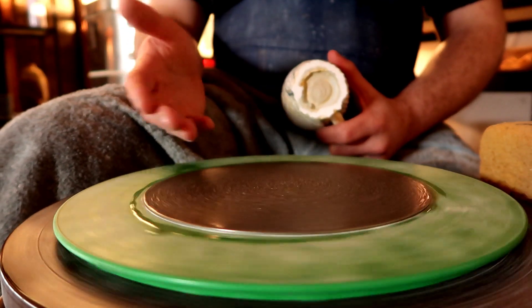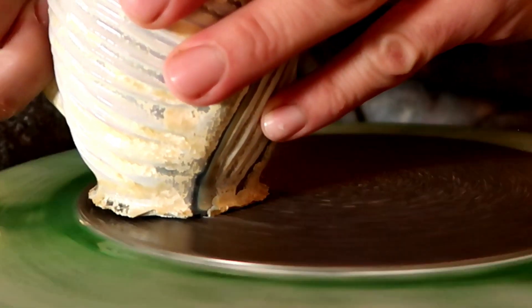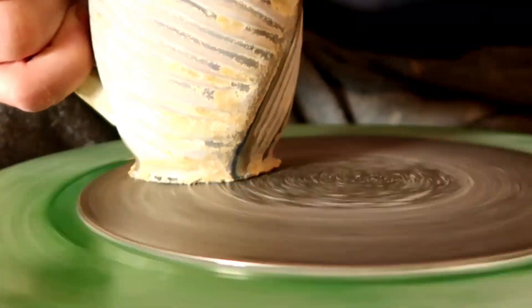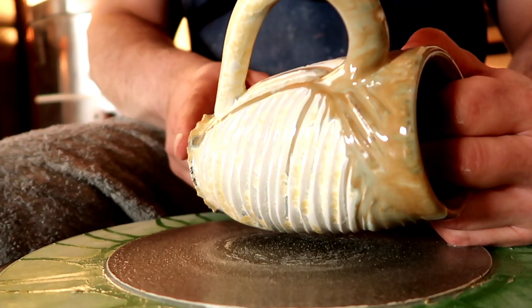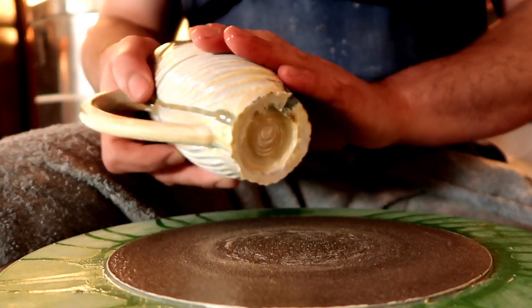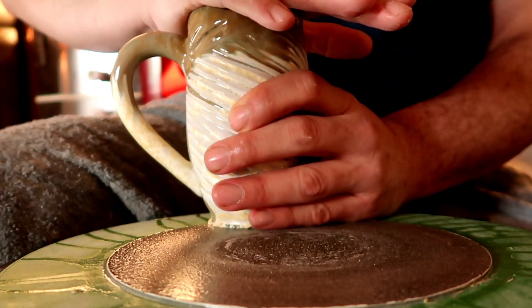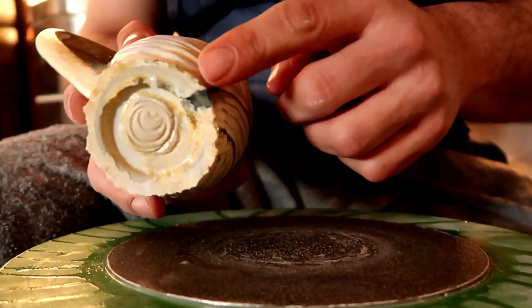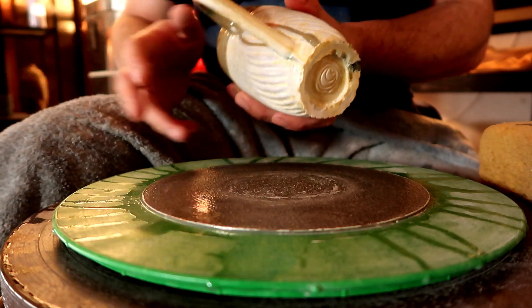Using one of these grind discs is actually very easy. All you really have to do is attach the bat to the wheel, get your pot, make sure it's nice and flat, and start grinding away. Now if you have a flange or something on your pot that goes outwards because it was sitting on your shelf, you might want to angle your pot. I usually put this at a very level setting as I grind just to smooth out my pots while putting pretty good pressure down on the pot as it spins on the wheel. But this time I really need to get rid of this extra silica and glazed glass-like material, and I want it to go upwards. I don't want it going down and I don't want it going out. So I'm just going to curve my pot at this angle. You can see that very easily on a couple of other things that I've already ground off.